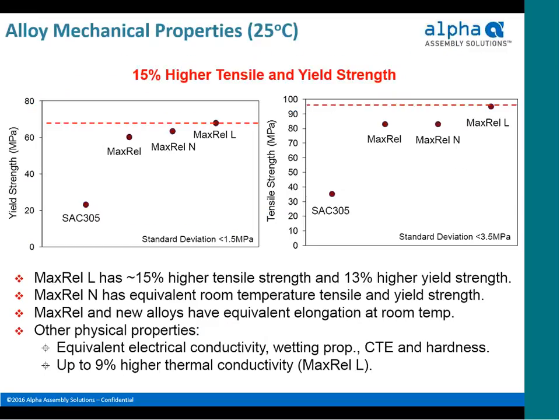Here's an example of a mechanical property. This is trying to show comparison of SAC 305, your standard lead-free alloy, with some high-reliability alloys. In this case, the graph on the left shows you the yield strength. So that's the ultimate strength, the ultimate amount of force applied before these joints failed. On the right-hand side is the tensile strength, which is the, actually, I'm sorry. Yield strength is the amount of stress applied before you get deformation. Tensile strength is the amount of stress applied before you get failure.